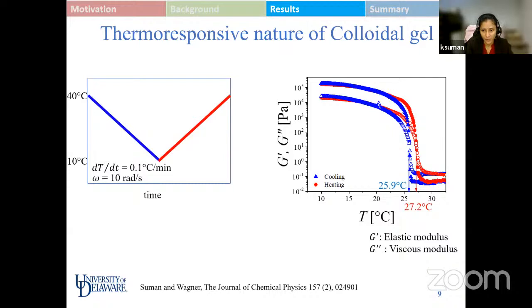So what I can anticipate is, if I increase the octadecanol chains on the spherical particles, there has to be a certain transition, or they have to interdigitate such that the attraction is able to lead it to a more and more attractive state, such that it enters the two-phase region. So we know in the vertical axis we had an increase in the attraction strength. The attraction strength between the chains of two particles should be strong enough so that it can lead to lower and lower states of energy. So if that is happening with an increase in the thickness of the coating, then we expect such behaviors to be more and more pronounced with an increase in the coating of octadecanol on silica particles, is what I can expect, but it is not something which I have explored right now.